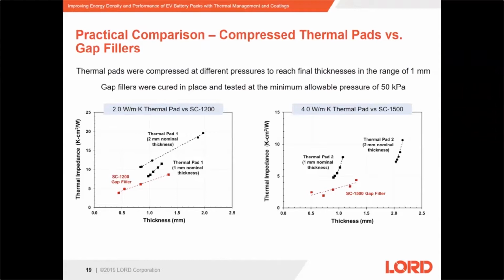Also, the slope of the black thermal pad lines is much higher than the red gap filler line, which shows that the bulk thermal impedance rises much more quickly as the thickness increases for the pads than it does for the gap filler. So in conclusion, gap fillers are able to cover a wider variety of gaps and have much lower thermal impedance than the thermal pads, even when they have the same or higher bulk thermal conductivity.